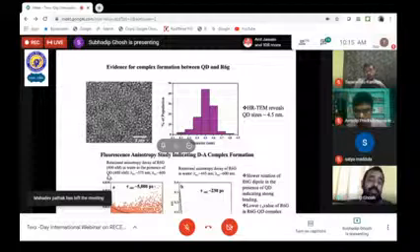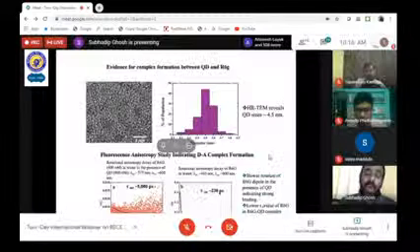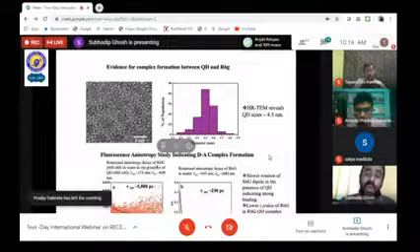Now here this curve is signifying that within 230 picosecond, and here rotation is very slow. So this is showing the rotation of the complex, that is rhodamine 6G along with quantum dot, and here it is showing the rotation of only rhodamine 6G. Now when there is only rhodamine 6G, there is no quantum dot, I can find the rotation is very fast, because obviously this rhodamine 6G molecule is very small.